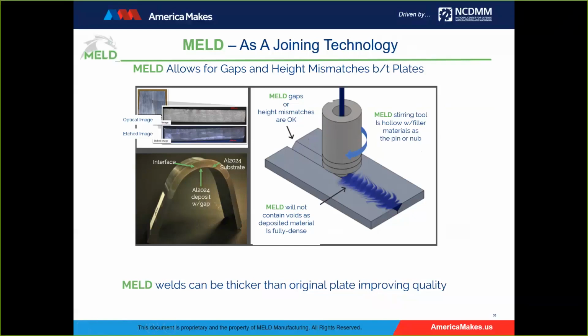We can put a gap in between the plates to do a thicker weld. So here's an example of two aluminum 2024 substrate plates. There's the plate. I'm sorry, that's not the plate. That's the end of the plate. So we have a gap here, a gap for a thicker weld. Of course, we passed the bend test.